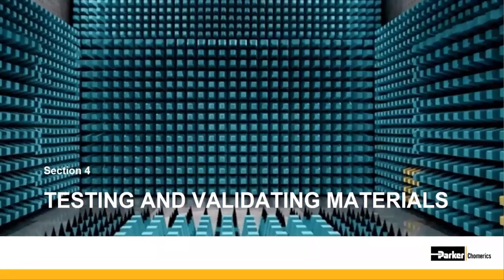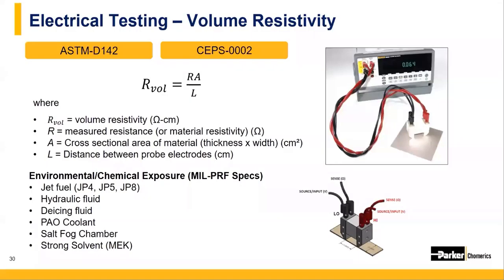Our last section before application examples is testing and validation of materials. Volume resistivity, shielding effectiveness, adhesion strength, and viscosity are the key properties that most people test for to validate material compliance. Each has a different test procedure and often an industry spec associated with it, such as IEEE, ASTM, or military specifications. Volume resistivity serves as the most common electrical measurement for conductive coatings and is the basis for most performance comparisons. It's measured using a resistance probe and requires a simple calculation based on the dry film thickness of the paint and the surface area covered by the electrodes on the probe.